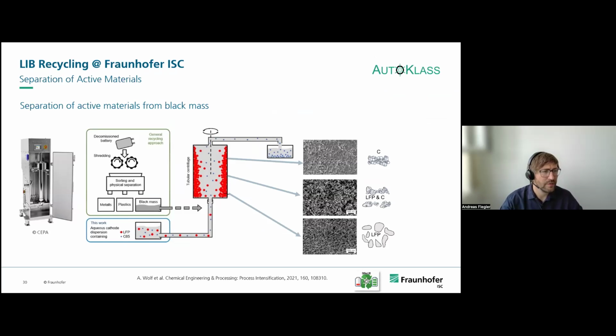For the separation of the active materials, we use a centrifuge technology. It's a semi-continuous centrifuge, and we pump in the black mass. So in this case, it's an LFP black mass with a carbon black. The centrifuge cylinder rotates, and the particles with the higher density or higher particle size end up in the centrifuge, and the smaller ones go into the centrate. And when you adjust the process parameters, you can retain the active materials in the centrifuge, and the carbon black will go into the centrate. This is a semi-continuous process. So when the centrifuge is filled, we have to stop it and remove the particles.